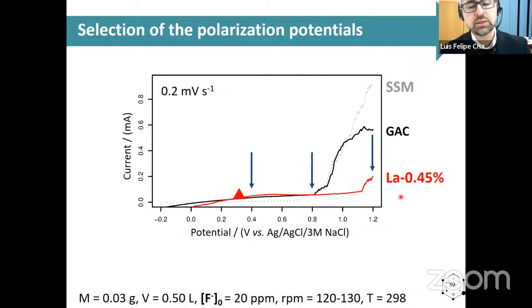The other interesting thing is that we monitor the concentration of lanthanum in solution. We noticed that the lanthanum doesn't decoordinate from the surface. So this is another advantage, because you have to take care that the material doesn't release this element into the solution. If it's released, you cause another problem of pollution.